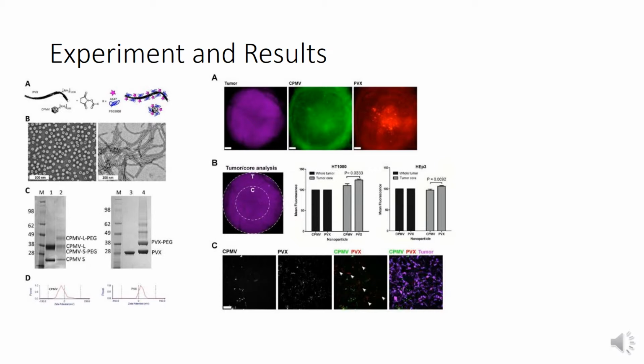This deeper penetration is hypothesized to be due to the filamentous structure of the PVX nanoparticles, along with the net positive surface charge of the VNP, which has been shown to lead to further diffusion through collagen, since negatively charged particles may aggregate in the positive collagen extracellular matrix.